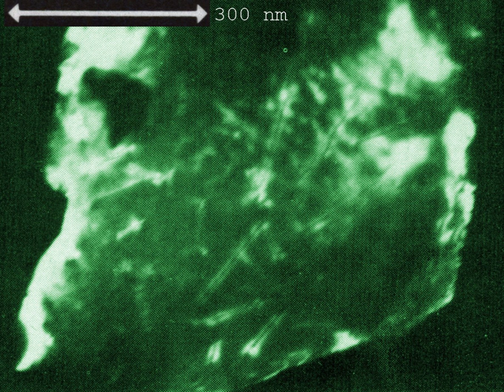Interpenetrating wire networks are fabricated by electrodeposition in multi-angle, track-etched membranes. Freestanding three-dimensional networks with tunable complexity and interwire connectivity are obtained. Segmented nanowires are fabricated by alternating the polarity during electrodeposition. The segment length is adjusted by the pulse duration. In this way, electrical, thermal, and optical properties can be tuned.